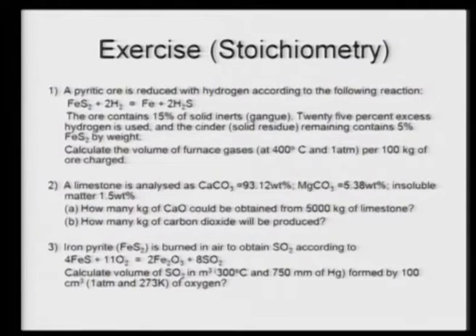So, in the reaction 25% excess hydrogen is used, and the cinder, that is the solid residue remaining, contains 5% FeS2 by weight. Calculate the volume of furnace gases at 400 degrees Celsius and 1 atmosphere per 100 kg of ore charge. Now, remember, you have to calculate the volume of gas at a temperature of 400 degrees Celsius. So, that point is important to note.